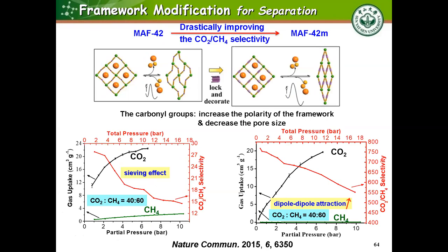With this modification, MAF-42M has much higher affinity to carbon dioxide, while the smaller pore size does not allow entering of methane into the pore. Therefore, the selectivity of MAF-42M for carbon dioxide versus methane is increased by about 30 times. This MAF-42M may be used for purification of low concentration natural gases, such as landfill gas.